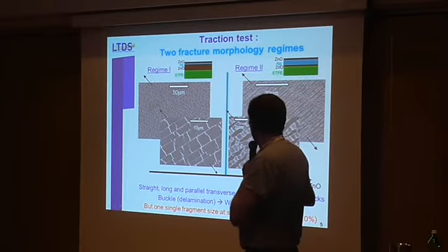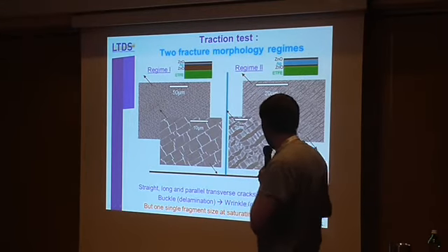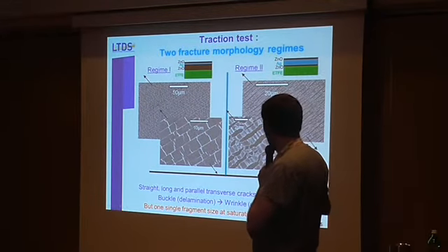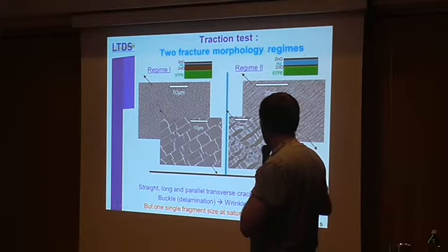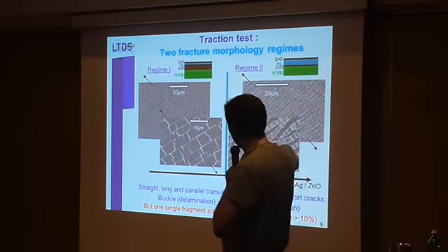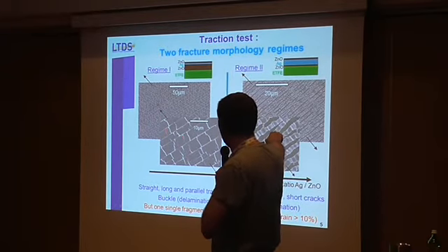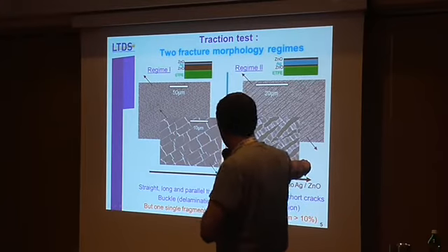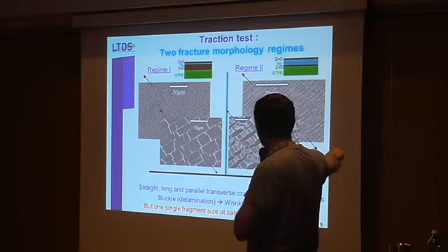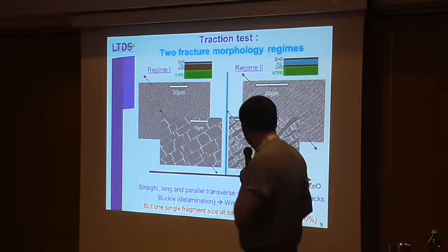And if you have a high ratio of silver to zinc oxide, you observe much shorter cracks that are wavy. And if you look at the other direction, due to Poisson effect, you can observe a buckle for low ratio, and you observe wrinkle with no delamination, even at high strain.